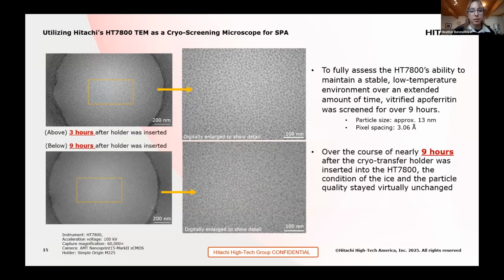But then after 9 hours, after the holder was inserted into the microscope column, we can see that the condition of the ice and the particle quality virtually stayed unchanged. So after 9 hours of imaging, the data is very similar to after 3 hours. So this is really great to know that we can achieve these conditions and still have reliable imaging capabilities during the full 9 hours of the system.